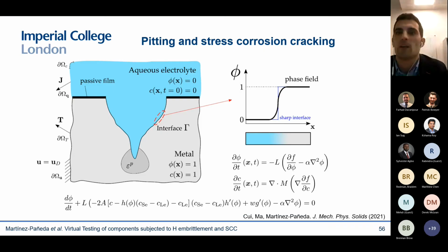The good news is that, again, we can make use of this phase field paradigm. Here, the phase field paradigm does not divide between crack and solid. Here, it divides between the aqueous electrolyte phase and the solid phase. So you can go from seawater when phase field is equal to 0 to the metal electrode when you have phase field equal to 1. And I won't get into the details for the sake of time, but basically you have two equations that govern the short range interaction. So the metal atoms detaching, so to say, this is what you use the phase field for. So this is the activation control corrosion, the process of the reactions that are happening there.